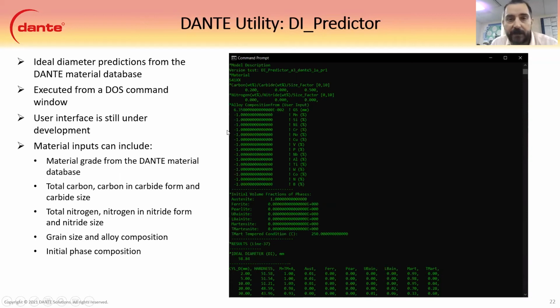The DI predictor we're still working on the GUI for it right now. But right now it's executed from a DOS window, the script base. And so it'll tell you the ideal diameter based on the input parameters, the same input parameters we just showed for the Jominy. And it uses the bar end, the Jominy, or the DI predictor, the ideal diameter to solve for all that. And so for this instance of 4120, we have an ideal diameter of about 58 millimeters.